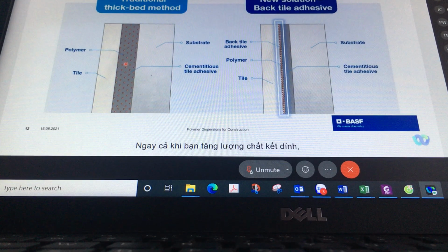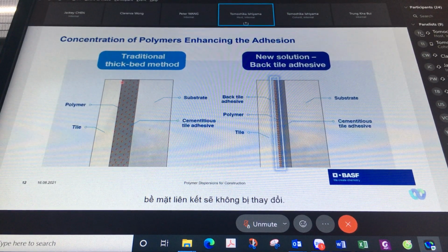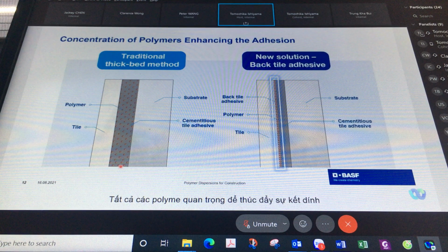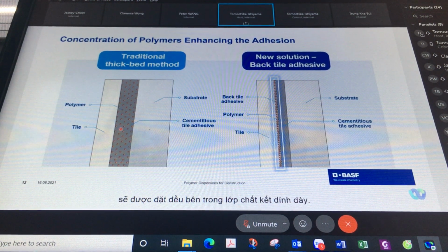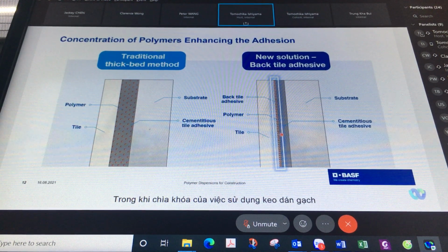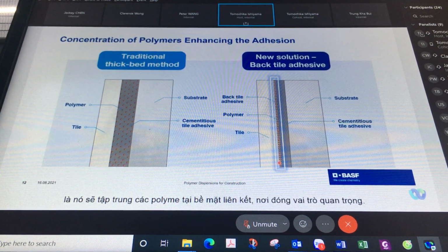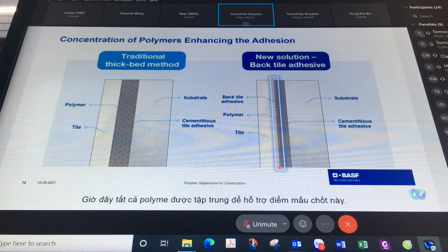The key of this method is to concentrate the polymers at the bonding surface. As you have seen, the tile failure occurs at the bonding surface between the tile and the tile adhesive. Even if you increase the amount of tile adhesive, the bonding surface will not be changed. All the key polymers to promote the adhesion will be evenly placed within the thick tile adhesive layer. Whereas the key of using back tile adhesive is that it will concentrate the polymers at the bonding surface, where it is the critical point of failure. Now, all the polymers are effectively used to support the bottleneck of failure.